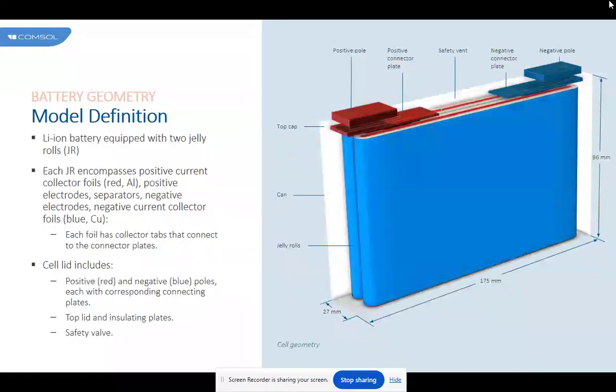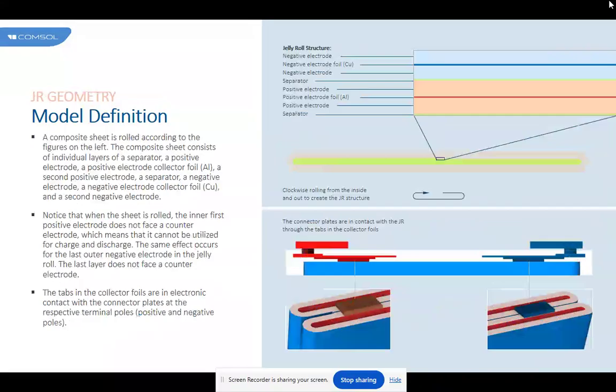About the jelly roll geometry model definition, a composite sheet is rolled according to the figure on the left. The composite sheet consists of individual layers of separator, a positive electrode, collector foil, aluminum, a second positive electrode, separator, a negative electrode, collector foil, copper, and a second negative electrode. Notice that when the sheet is rolled, the inner first positive electrode doesn't face a counter electrode, which means that it cannot be utilized for charge and discharge. The same effect occurs for the last outer negative electrode in the jelly roll. The last layer doesn't face a counter electrode. The tabs in the collector foils are in electronic contact with the connector plates at their respective terminal poles, positive and negative poles.